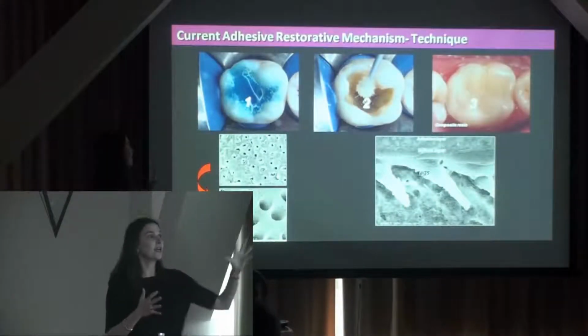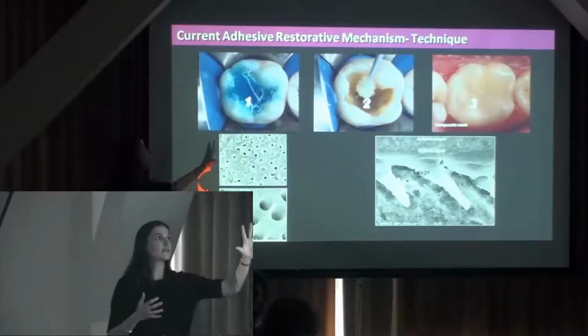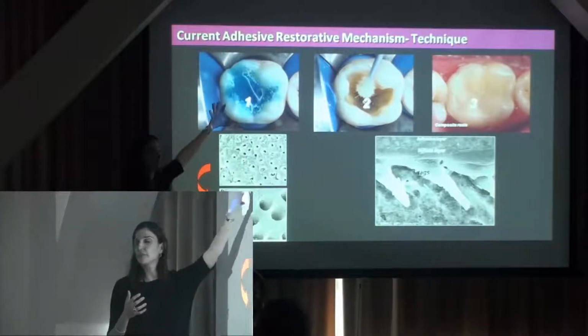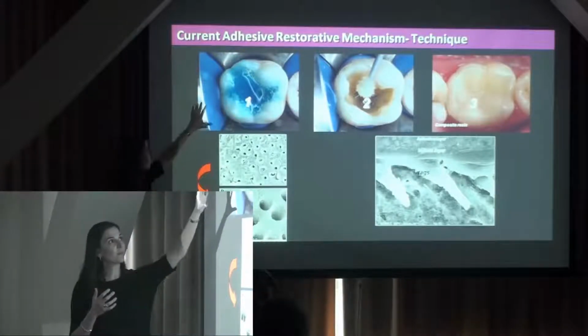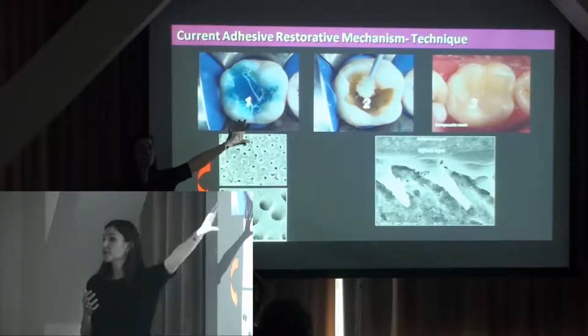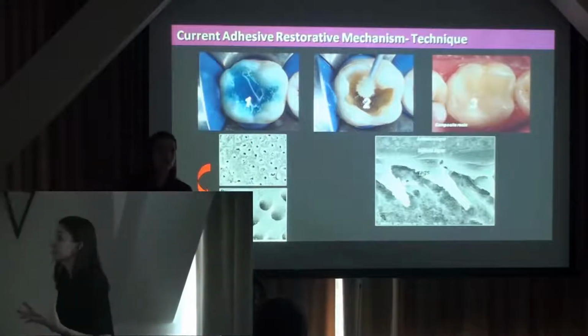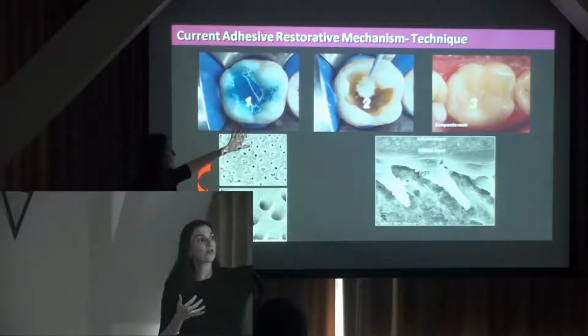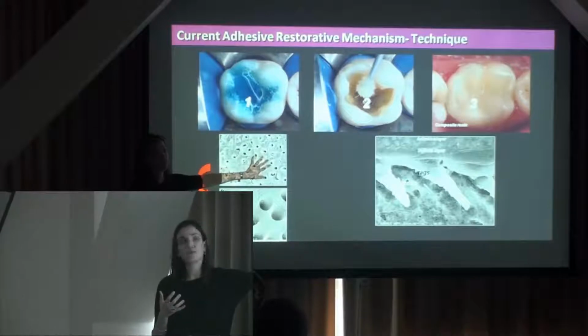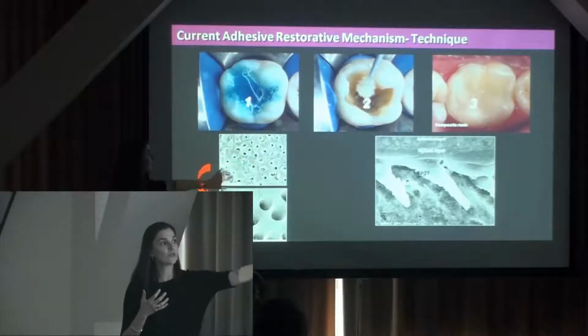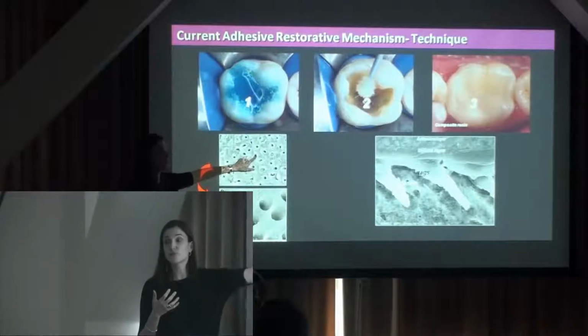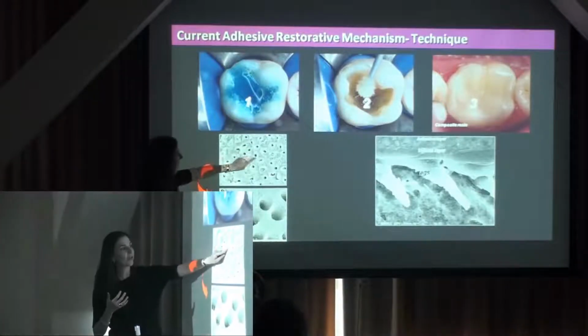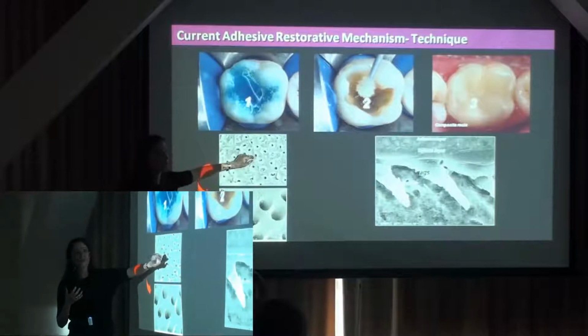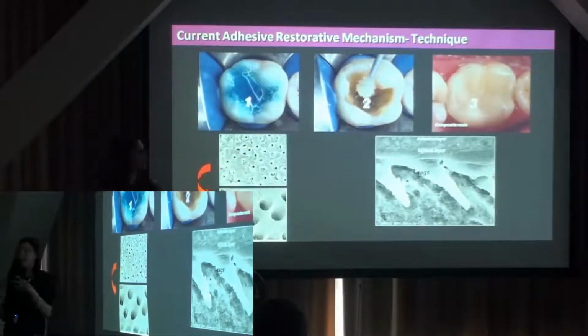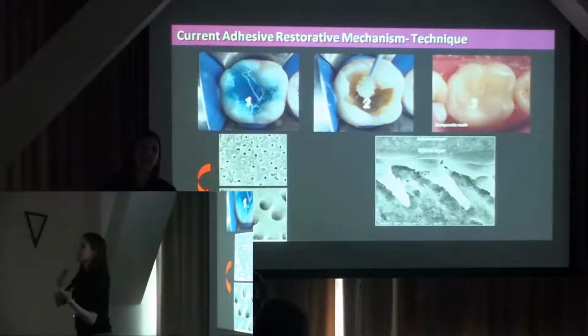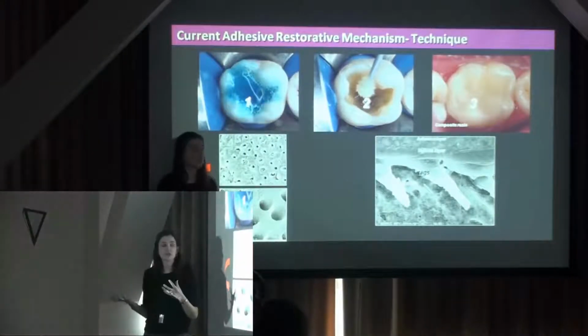This is just to simplify what the clinical steps involved nowadays are. So we have a tooth, we clean it up, we remove the decay, we get that prep ready, and we use phosphoric acid at a concentration of 37%, and we need this process so we can superficially decalcify the surface of the tooth. So this is the surface of the dentin. What we have are these dentinal tubules, they're hollow, and we have a highly mineralized intratubular dentin, and in between we have this mix of hydroxyapatite and primarily collagen.